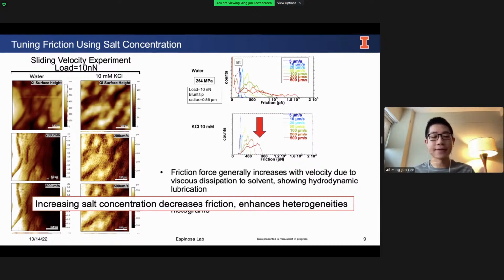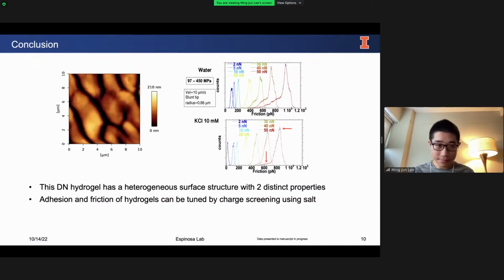To summarize this slide, I'd like to have convinced you that we can decrease friction on these hydrogels by increasing the salt concentration that we immerse them in. And as a side effect, we are also enhancing the heterogeneities of these double network hydrogels.